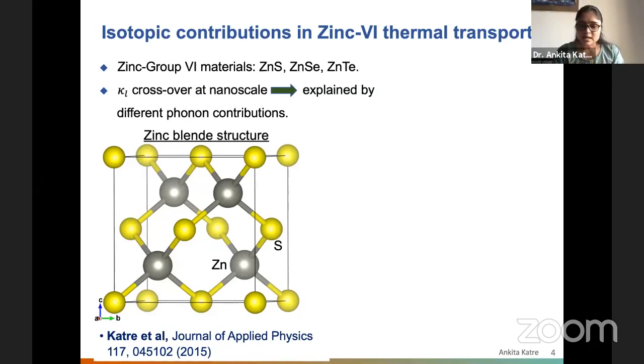So zinc sulfide, zinc selenide, zinc telluride, the family of these materials called zinc chalcogenides, are in the zinc blend structure, the low temperature phase. So this is basically the classic zinc blend structure. For zinc selenide, we will just replace this sulfur with selenium, and for telluride it will be just tellurium here.